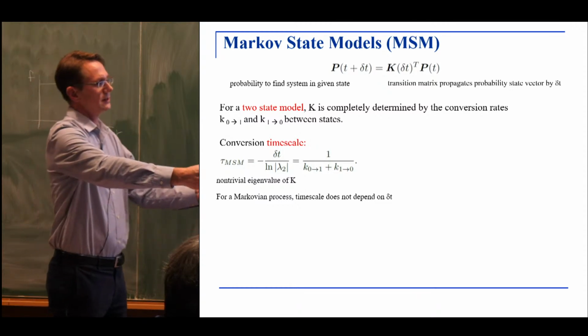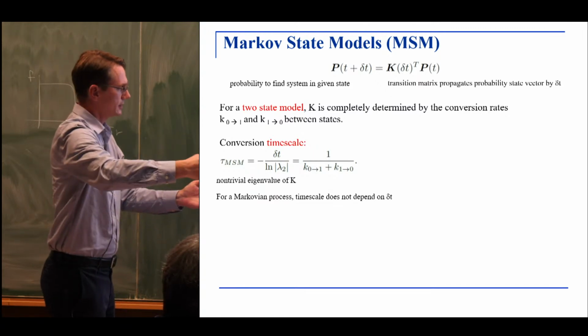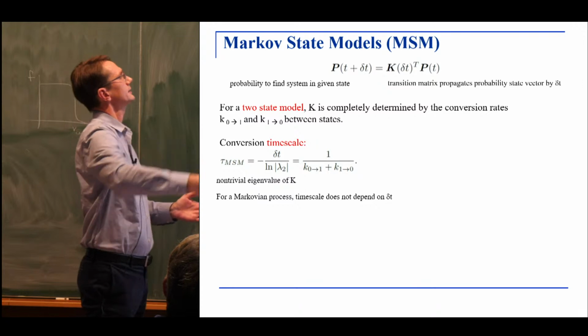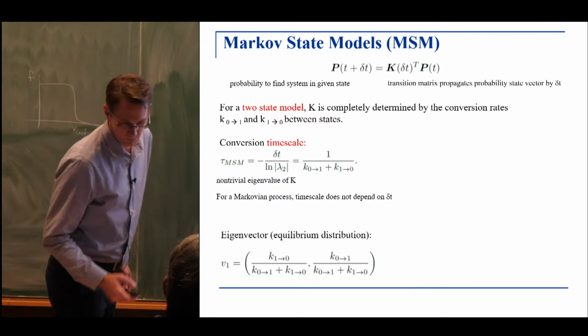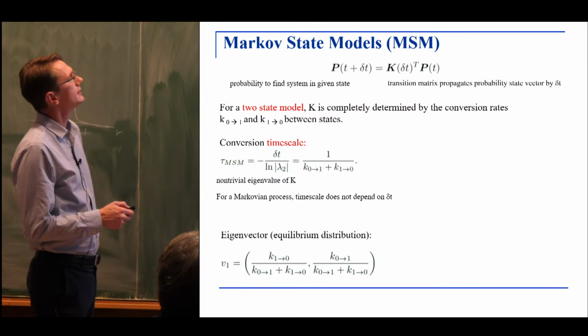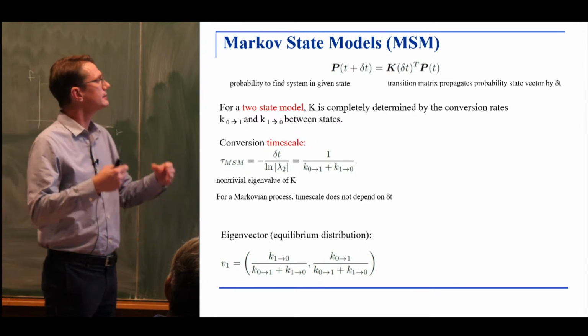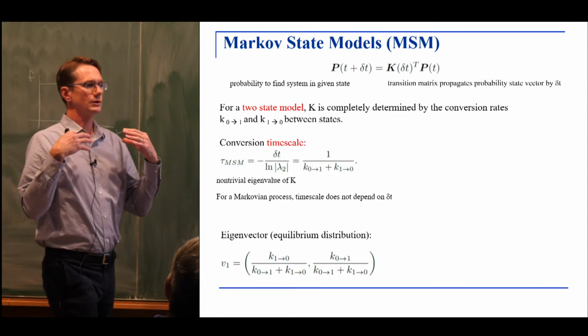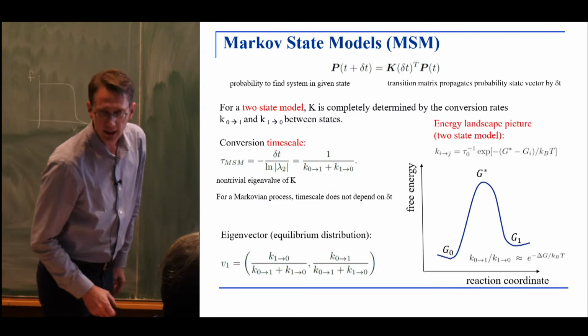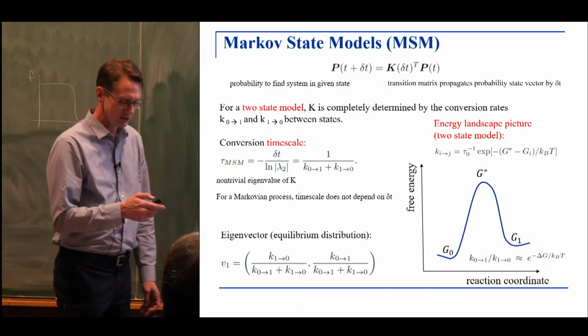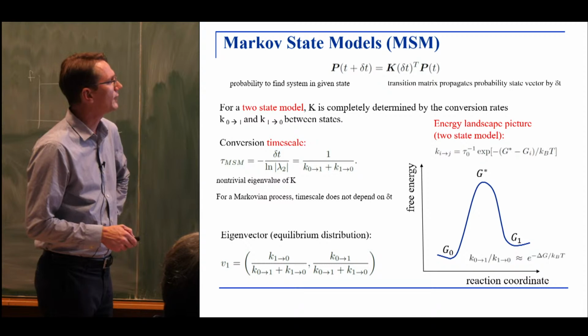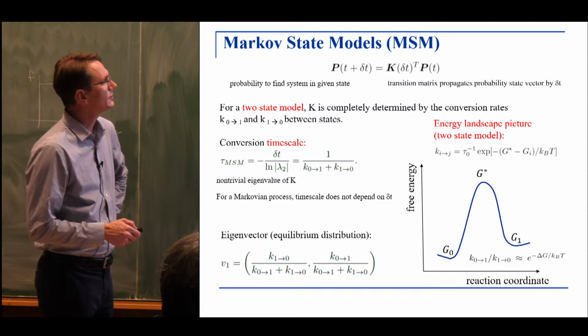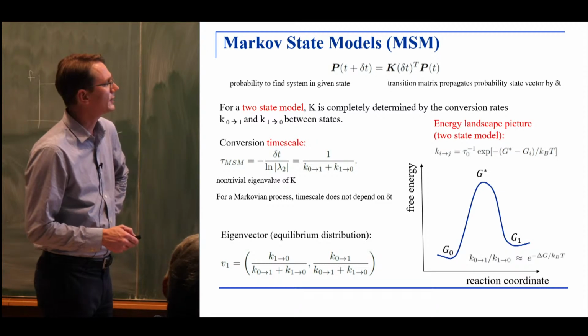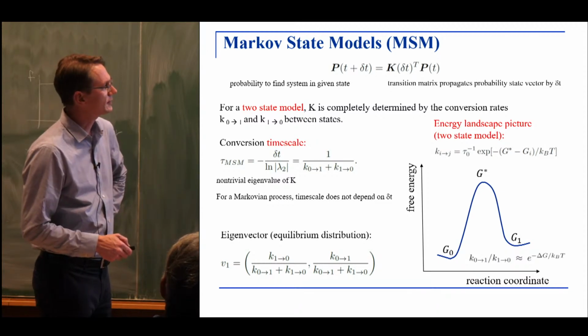So we have to make sure that we coarse grain sufficiently so that this memoryless dynamics is indeed obtained. All right. There is also interesting information in the eigenvector of this matrix, and that is the ultimate equilibrium distribution that this Markov state model would evolve to at long times. And if you would like, you can think of all of this in an energy landscape picture. So if you ascribe two values of a free energy, G0 and G1, to our two states, and we imagine some free energy barrier in between with magnitude G star, then we can simply write the transition rates in an activated fashion, in an Arrhenius form, and the ratio of the forward and backward rates is just related to the free energy difference of the two minima.